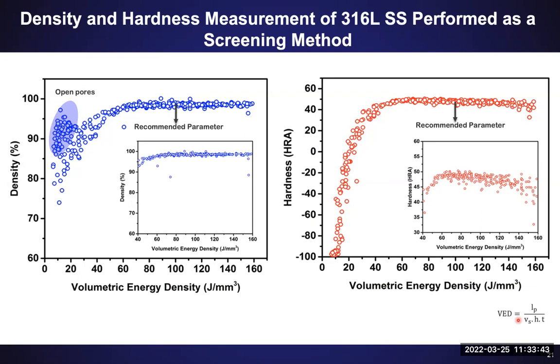As you can see from this plot, most of the samples that were printed had densities that were less than desirable. In fact, here's a region highlighted in the plots where when we looked at the samples, we knew that the samples had open pores. So we decided we do not want to get samples for dynamic testing from this area. We chose some samples from the region where we got maximum density.